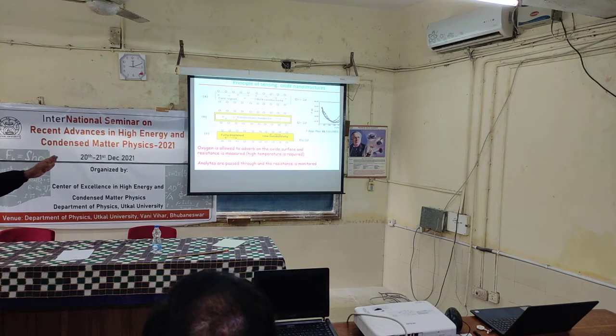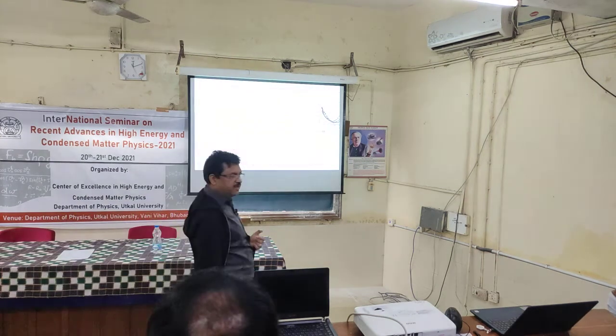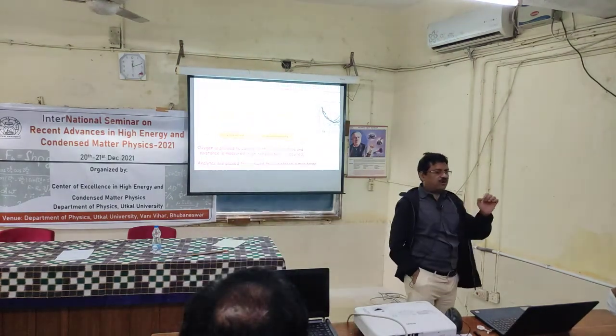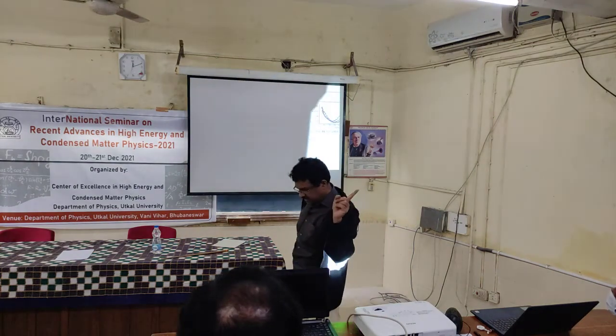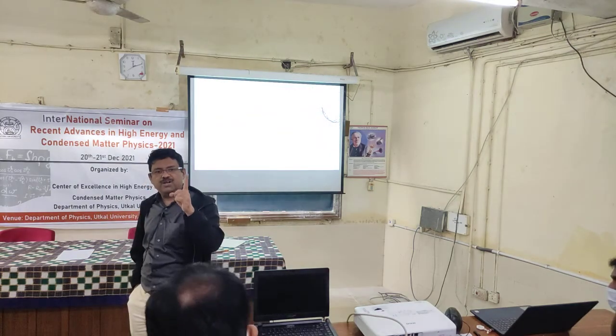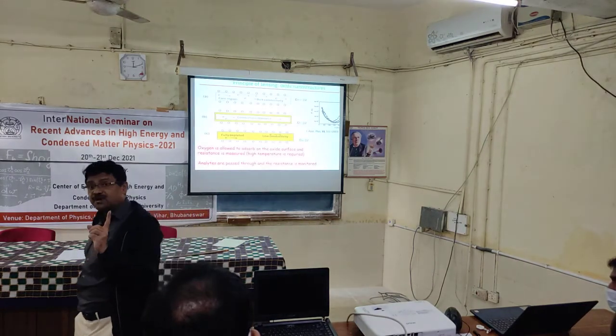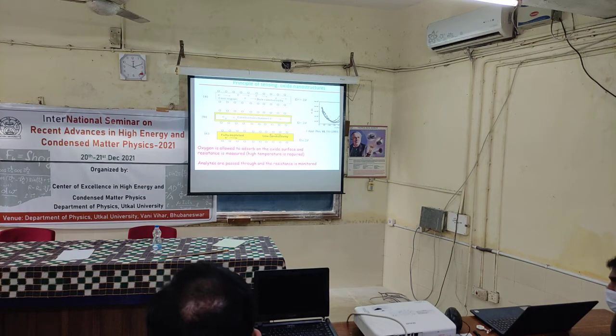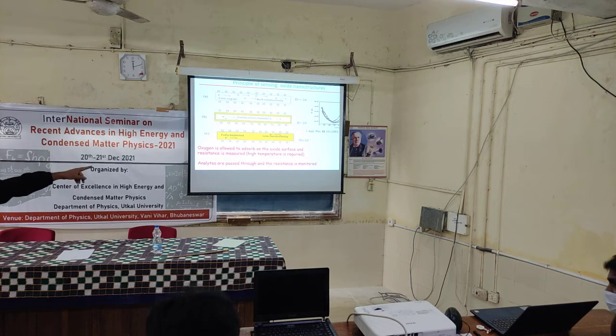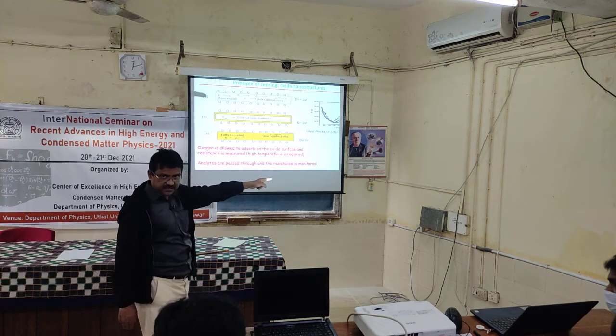What we were not able to see is that the experiment was performed in oxygen atmosphere. What we deal with in the textbook, even though it is not mentioned, when they talk about resistance versus temperature of metals or semiconductors, is either in an inert atmosphere or in vacuum, not in oxygen atmosphere. If you do the experiment in oxygen atmosphere, something unusual may be seen. Here, R versus temperature up to 150, the experiment is performed in oxygen atmosphere. As we raise the temperature, the resistance is decreasing.